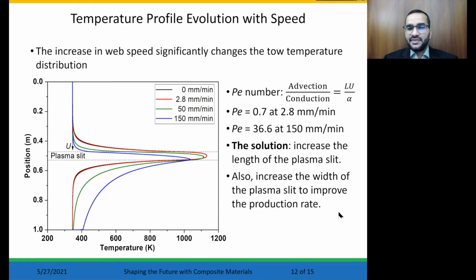This would suggest that the throughput of graphene deposition on carbon fiber tow can be increased when the plasma region is enlarged. Also, the production rate can be increased by processing multiple tows simultaneously using a wider plasma. Finally, it's important to independently control the temperature in the pre-plasma region and post-plasma region to allow carbon fiber tow annealing before graphene deposition and cooling after the graphene deposition.